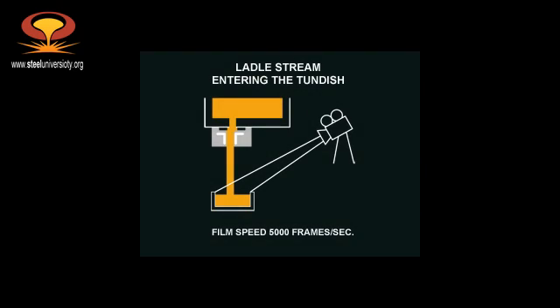The white patches — the lighter patches — that we see on the steel stream correspond to re-oxidation, which takes place extremely rapidly. This next view shows the impact zone in the tundish where the ladle stream enters. The dark material floating on the steel in the tundish is freshly made slag — slag formed by the re-oxidation of molten steel, with air drawn into the tundish by the falling stream generating freshly made slag.